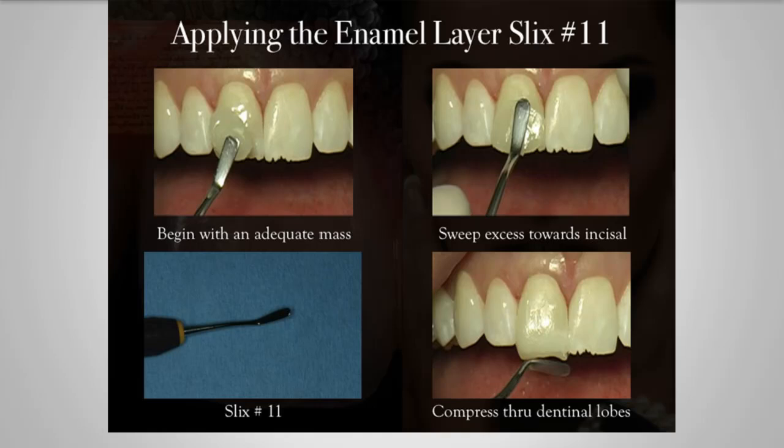One thing, everybody probably knows the term, you don't want to be going pat, pat, pat or hearing tink, tink, tink. We hear so much complaint that composite materials have a lot of porosity in them, when in fact it's the instrument that we've chosen that actually creates the porosity. Well, there are some bad composites out there. But the majority of them by the bigger name companies are not going to be laden with all kinds of porosity inherent in the syringe. It's the way we apply it and the instrument that we use that actually creates the porosity and the problem.